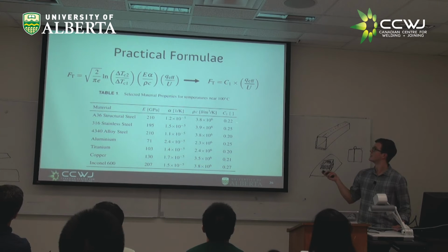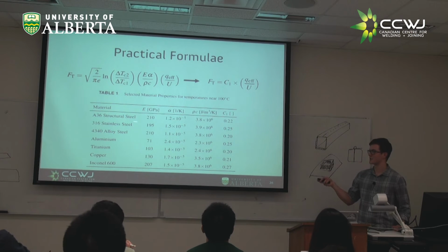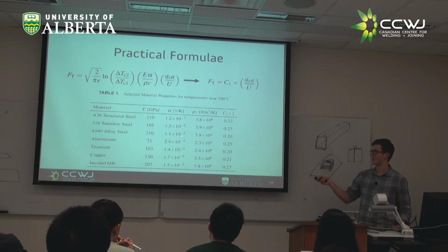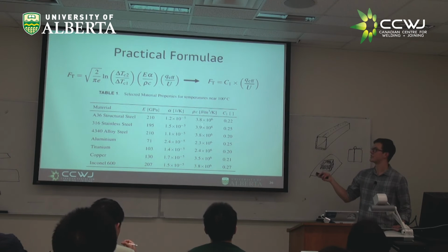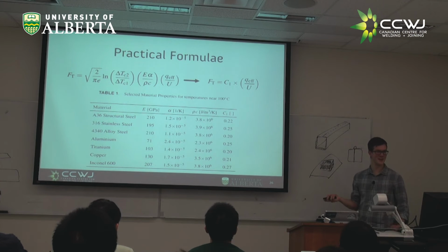Now, if you look at all these different constants, we went from structural steel to stainless steel to alloy steel to aluminum, titanium, copper, Inconel. We have some properties changing by a factor of 3, some properties changing by a factor of 2. Maybe the least changes in our specific heat capacity, but C1's always in about the same range. Now, this is more of a chemistry problem than a materials problem, but we see that we have E alpha here.